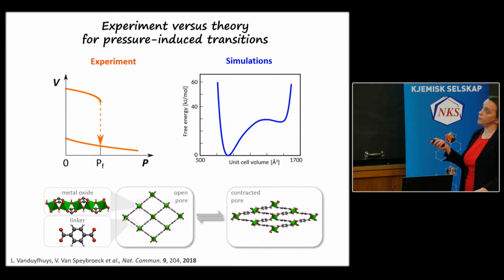It's an empty framework here. So this is what you can see from experiments. So it's a volume versus pressure diagram. And here you can see you start with big volume. So you apply pressure, basically, and it can close the material. And we can indeed also construct this, but we can also construct the free energy diagram. We see two minima here.